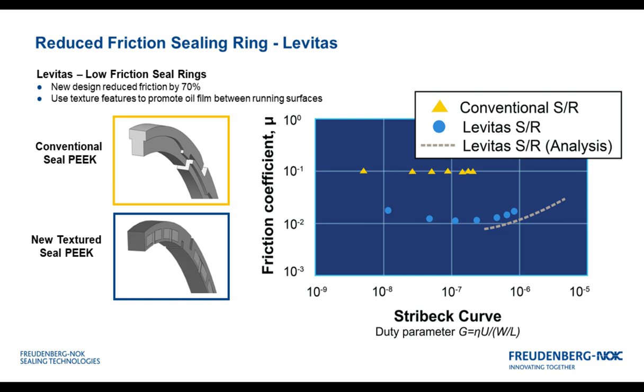To move on, I'll talk a little bit about the Levitas seal rings. These are using some of the same technology, but in this case, not a thrust bearing, but a sealing application. Here we have two examples of seals. The first, in yellow, is a traditional seal, used for many years in transmissions. We call it a T-shaped seal ring. You can see the friction coefficient on the graph is relatively flat as you change along the Stribeck curve. You don't get a significant shift in friction as you increase the speeds.